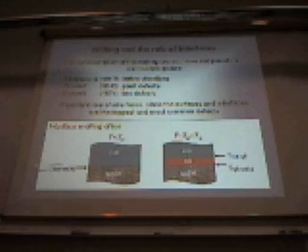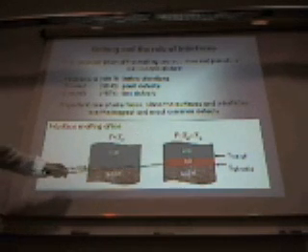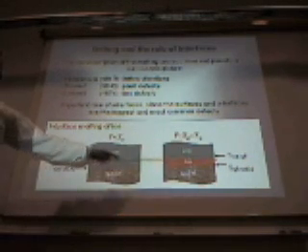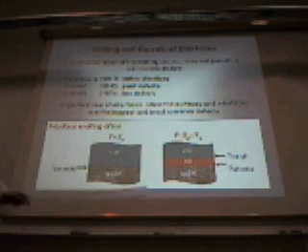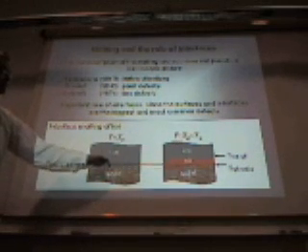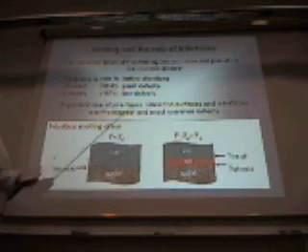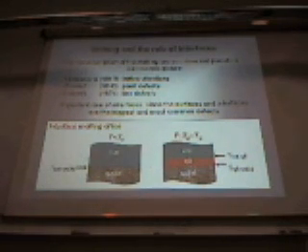So you have ice in contact with something, could be a solid, could be vapor. Then you have, in a very simple continuum description, a surface energy between the two. Now at a certain temperature, as we've heard this morning already, it might be better to actually have another interface between those two and put in a liquid wedge, so to say, in between, and that still lowers the total energy, although you have the price of the latent heat, which you have to put into the system to actually turn this ice piece into a liquid. So it's still better because you lower the interfacial energy in a certain temperature range. Not for all systems, but for some.